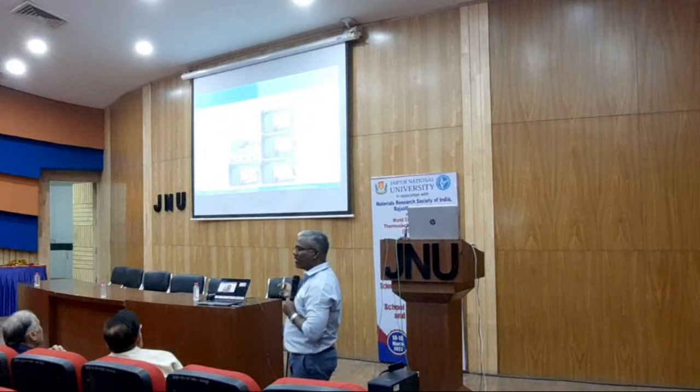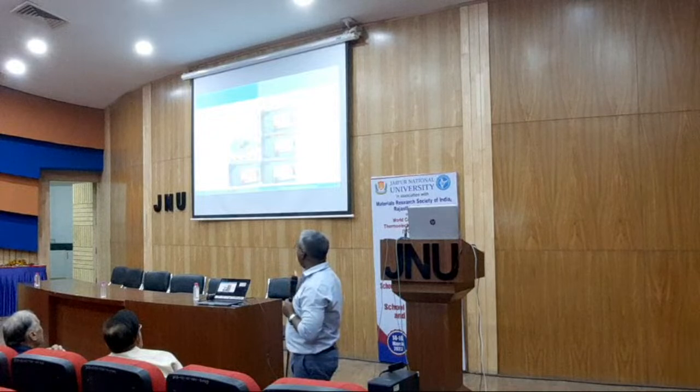And so now we can show this. Here we can see the PN junction which we created as a single device. From this device, you can see in the first figure, when people press it with a finger, the device shows 1.1 millivolt for one PN junction. And when we keep pressing and stress is applied on the device, we can see 20.6 millivolt generated. Whenever stress and strain happen on the polymer material, it acts as flexoelectric. When you touch directly, it acts as thermoelectric. So with this hybrid nature, we can take the potential power.